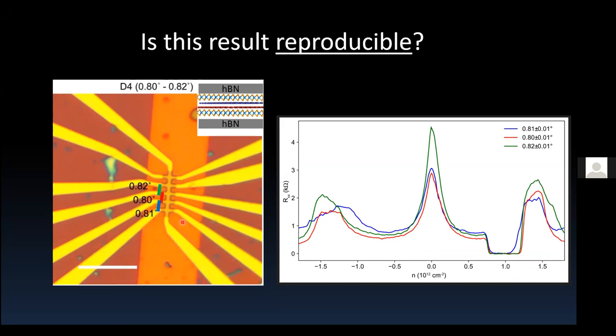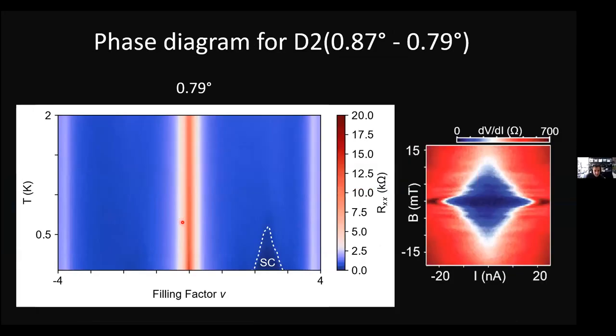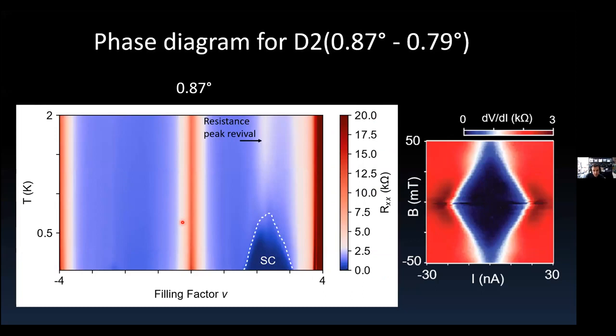More questions? Yeah, Stevan, I've got a question. One of the samples that you showed has superconductivity that completely straddles nu equals 2, and then you had the emergence of this peak at higher temperatures. Oh yeah, this is 0.87. That seems really unusual. I could imagine a scenario where the symmetry is not broken at nu equals 2 at low temperatures, and therefore you don't see the insulator, but then you see the superconductor because there's some broken symmetry at 2 plus whatever. But here it really looks like the ground state is simply superconducting at nu equals 2. So I was wondering whether you had Hall data for this sample and what it looks like.